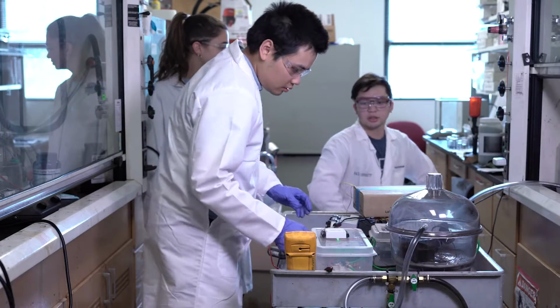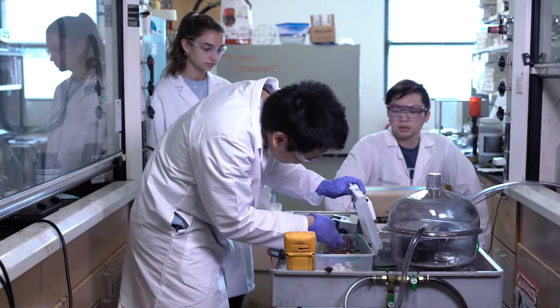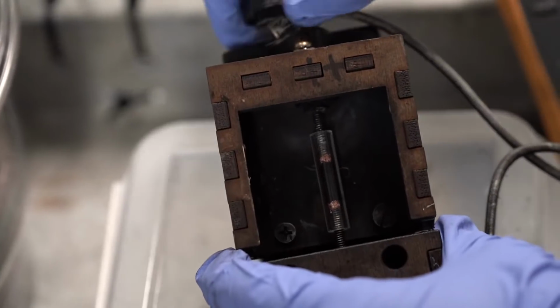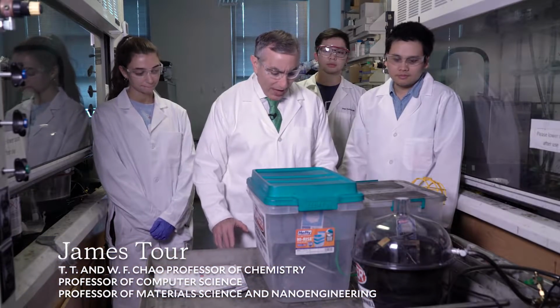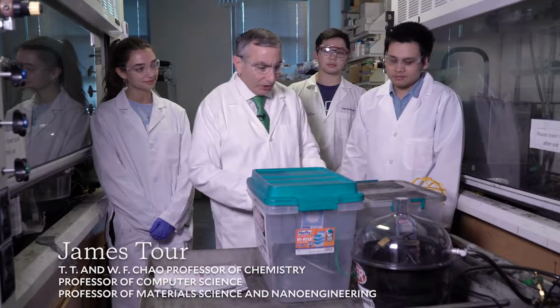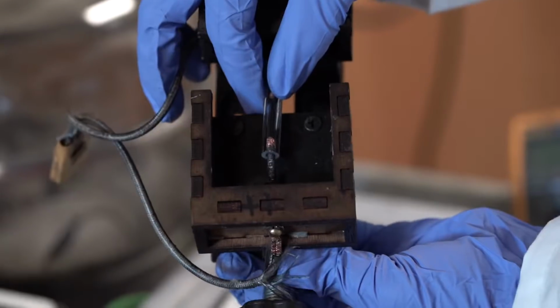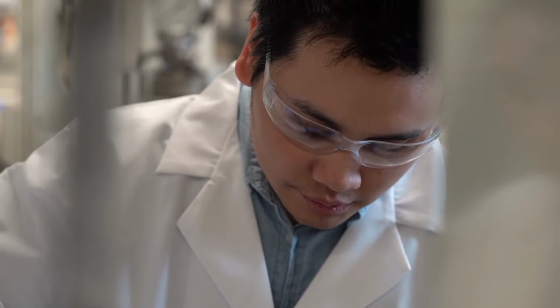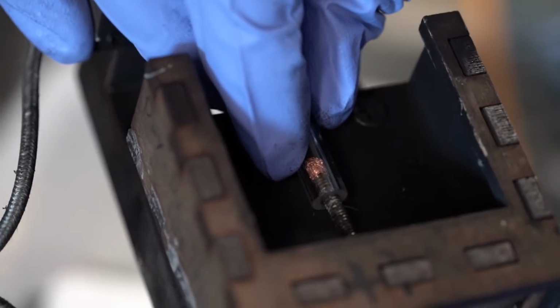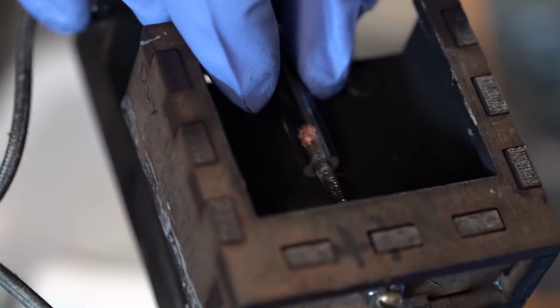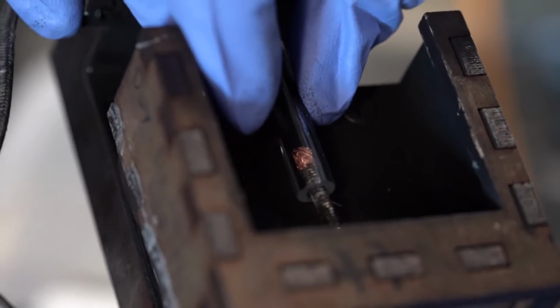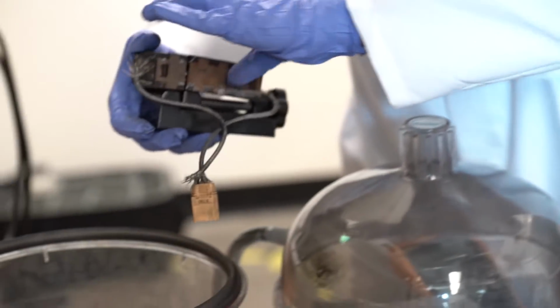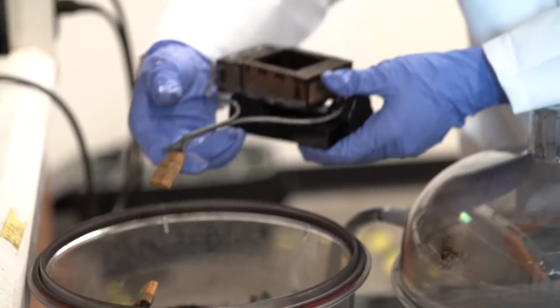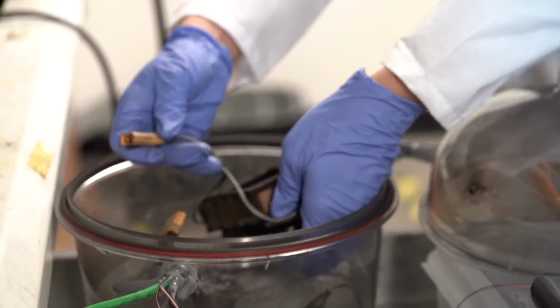In the bottom of this cart, there are banks of capacitors that get charged up. The wall current charges up these capacitors. Then what happens is that goes through some electronics, and then it goes to two electrodes. And then when Dewey pushes the button, we have a high voltage across this, and then a current will pass through this with enough energy to break every carbon-carbon bond in the system. And when that breaks, it's going to reconstruct as graphene.